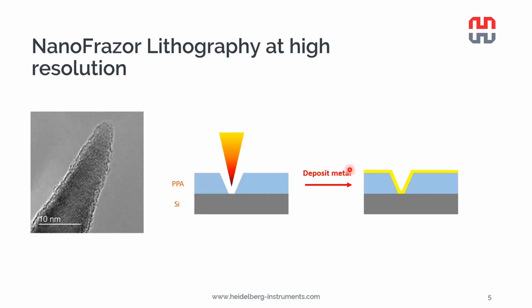Now we have a small problem with the NanoFrazor because we are using these ultra sharp heated tips for removing polymers from the samples, and we would end up, as we can see in this illustration, with sloped sidewalls. And if we would deposit metal everywhere on the sample, we would have a continuous film of metal, and the solvent could not remove the PPA from underneath. We would be just left with the original structure like that in the final sample.